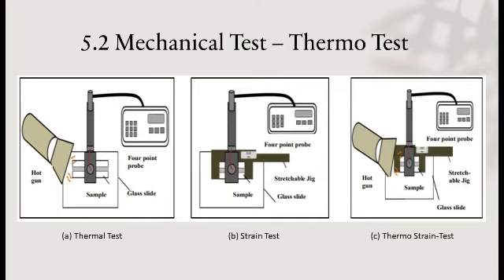As for the thermal strain test, the test is done by stretching the inks at various levels, as in the strain test in figure B, and then concurrently heating from room temperature to low temperature, intermediate temperature, and then high temperature for 30 seconds before deploying the 4-point probe to measure the resistance. Next, we move to the conclusion.